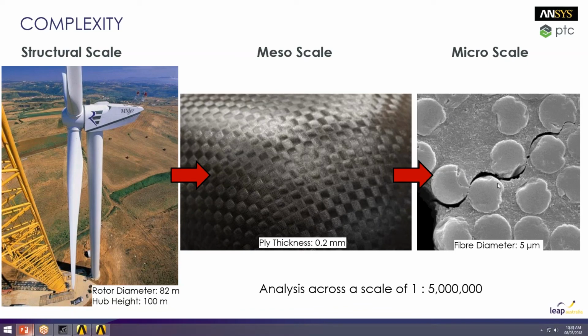In this case, microns, 5 microns. And we're looking at some scanning electron microscopy of a composite material. So these circles are the fiber itself, and you can see it embedded in the matrix. And so the failure of this material is actually governed by this tiny little crack, which is running its way through the matrix. So we need some way of understanding material response at these tiny little scales, which we can then efficiently scale up to the full structural size.